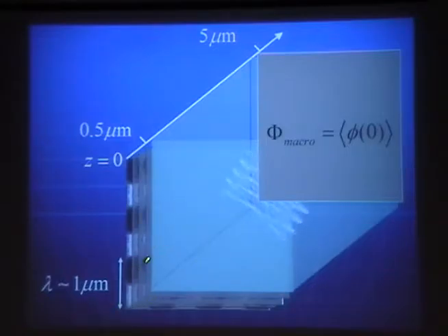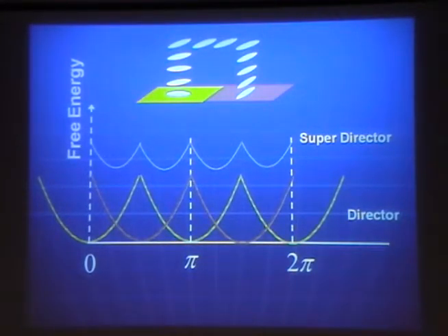And once you establish this orientational state, then you can apply an electric field. That drives the orientation in the bulk. And that changes the orientation in the bulk that eventually induces the orientational buckling on either of the 2 types of domains. And you can extend this same idea to many different patterns, as I schematically illustrated initially.